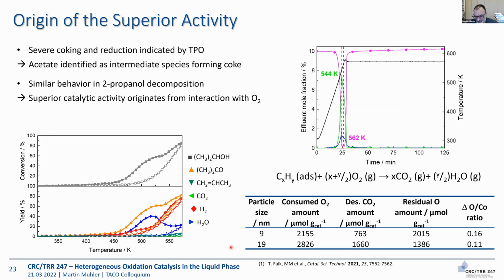And now we can again solve the mass balance after running steady state catalysis. That was quite challenging for Tobias Falk, who did all these studies. The question is seemingly simple. We know how much oxygen we consume. We know how much CO2 and water is formed. Shouldn't we be able to calculate the amount of oxygen that is used for reoxidation of the catalyst? In principle, yes. And what this table tells us, yes, the larger particles actually need less oxygen for reoxidation. That means they remain in a more oxidized state. That means this reducing acetate poisoning is less severe. That means they are faster reoxidized.